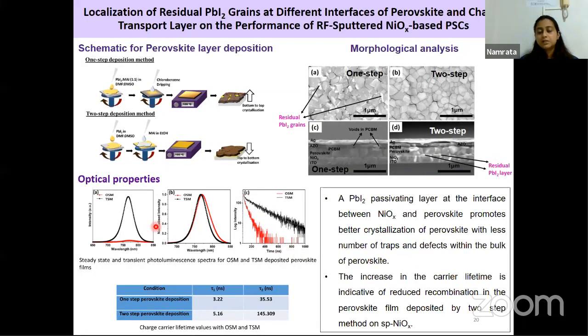So the difference is quite clear that in the one-step deposition method, we have the residual PbI2 on top of the perovskite, whereas for the two-step, we have the residual PbI2 at the bottom, which is very clear why, because we have a PbI2 layer at the bottom in the beginning. So when we check the optical properties, again, we see the difference that when we measured the steady state photoluminescence, we observe that for the one-step method, the PL peak intensity is quite low, whereas for the two-step method, it is much enhanced.